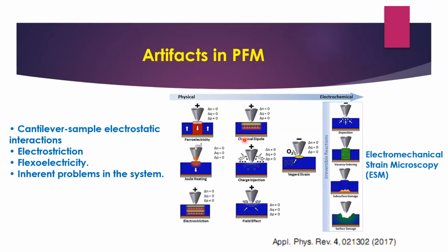And for this topic, several techniques were developed to detect this kind of artifacts. These artifacts can arise in different ways, such as cantilever-sample electrostatic interactions, electrostriction, flexoelectricity, and inherent problems with the system.